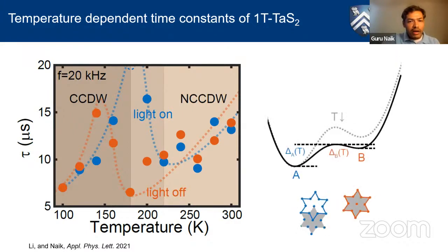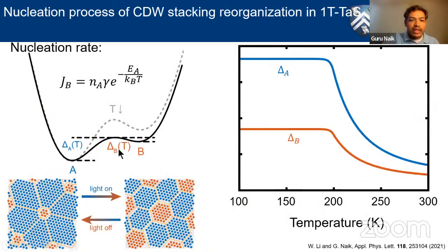So what we started our thought with was, let's assume that there is an energy cost or two different stackings here. There can be a transition between them through an energy barrier. Just like how nucleation theory assumes that there are two different states, and then there is a barrier that it has to go through for going from one to another. So if we assume this kind of nucleation theory model, then we could explain this behavior. So in fact, what we did was, let's assume that the rate of CDW domain switching from A to B versus B to A can be written down simply by the nucleation rate, which we know from nucleation theory, and then just write down the rate equations in steady state. And if we do that, we can reproduce exactly the time constants.